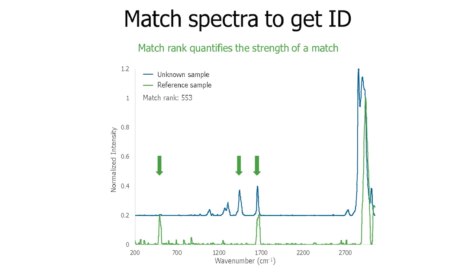In our upcoming case studies, we're going to talk about quantifying the match to get the strongest match possible. So I want to tell you a little bit about how Hound does that. Match rank is the parameter that Hound uses to quantify the strength of a match between your unknown particle and the reference material in either our default or your custom databases. Match rank is calculated by multiplying the Pearson correlation coefficient by 1,000. So you end up with a value between 0 and 1,000, with values closer to 1,000 indicating a stronger correlation.